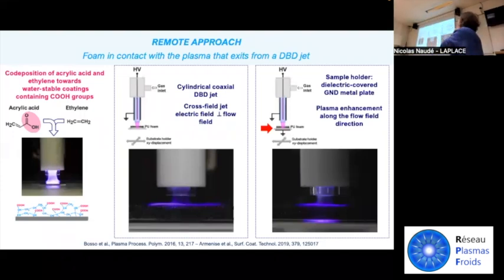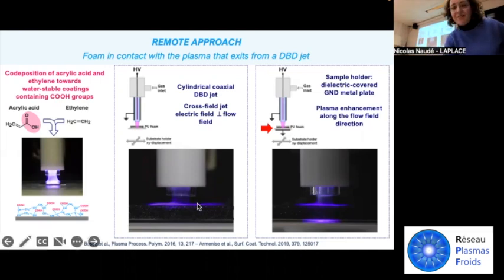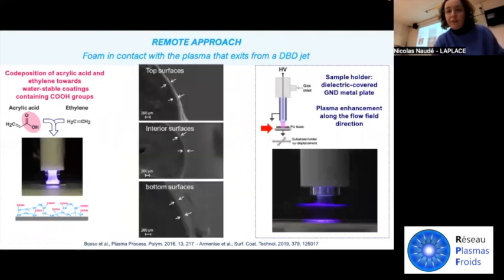For instance, we utilize here a very simple strategy. The key is we use a sample holder that is a dielectric covered grounded metal plate. In this way, we obtain an enhancement of the plasma along the flow field direction. And even if it's not clear from the picture here, we were really able to obtain the plasma also inside the foam throughout the porous structure. Here you can see some SEM observations we performed on the top surface of the sample, on the bottom surface, and also the interior of the sample, and we were able to obtain the coating throughout the sample.